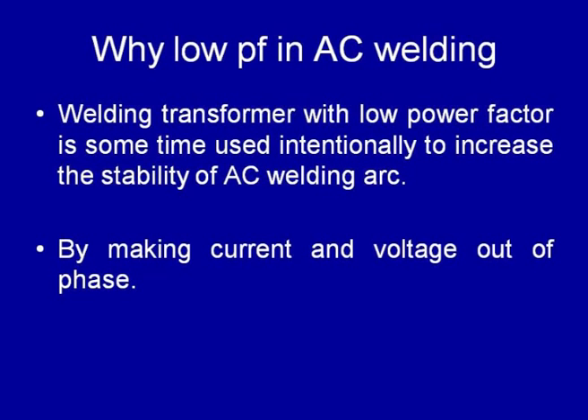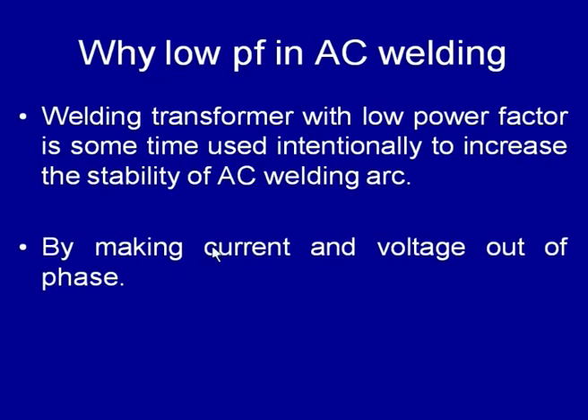Welding transformers with low power factors are sometimes intentionally used to increase the stability of the welding arc, especially when AC is used. This smooth stability is obtained by making the current and the voltage pulses out of phase, so that when the current is 0, the maximum voltage is available for reignition of the arc. So, especially in the case of AC welding,